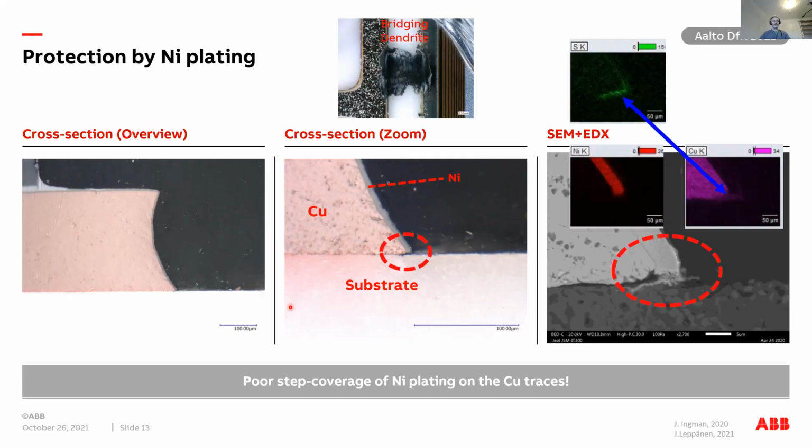There, time of wetness was defined as 80% relative humidity when the temperature is above 0. So this highlights that these rules of thumb, or even standards, are not always valid. It depends on what kind of mechanisms there are.